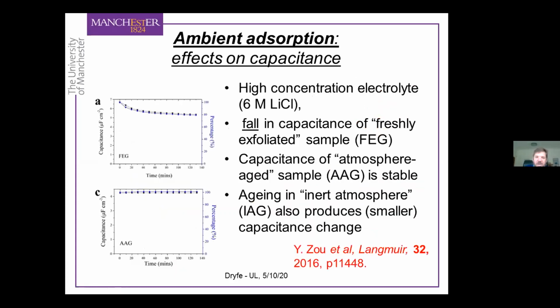And we also see this change in the capacitive response. We're working at high electrolyte concentrations, i.e. using the same trick as Gerischer, so that we can avoid having to worry about the diffuse double layer capacitance. We only have to consider the capacitance of the solid and the capacitance of the Helmholtz layer. But you see that the capacitance of the freshly exfoliated graphite, that's what FEG stands for, falls by about 20% over time, which is basically due to this adsorption effect of organic materials. It reaches a kind of quasi-steady state after about 40 minutes. Whereas if we take the already aged sample and measure its capacitance, it's pretty stable. It's quite a lot lower, but the value is completely stable because obviously the material has already aged and reached its new equilibrium value.